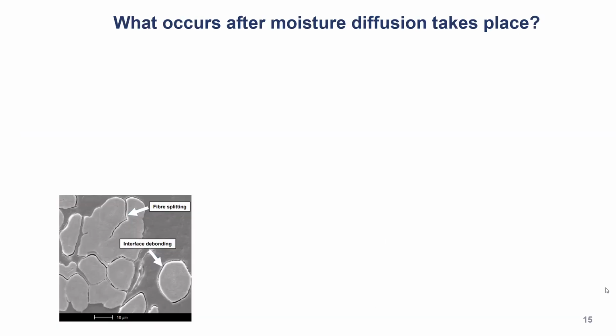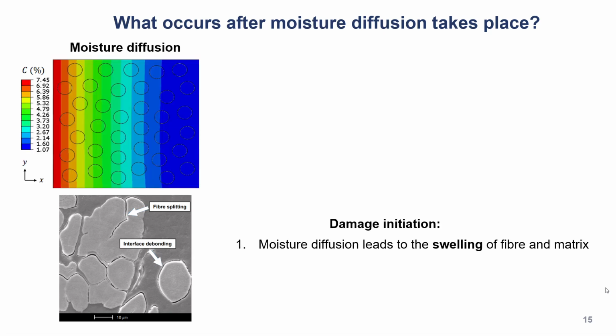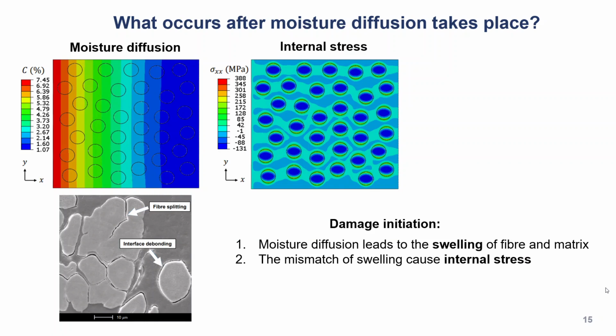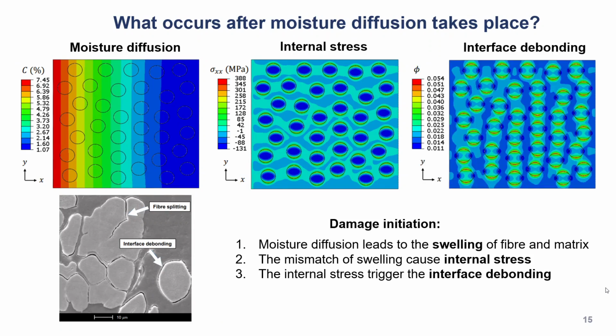The first question we want to ask is, what occurs just after moisture diffusion takes place? If you look at the experimental results, you can see some fiber matrix debonding occurs. And this can be explained by this failure sequence. You have the moisture diffusion. This can cause internal stress due to the mismatch between the fiber and matrix coefficients of expansion. They can have different internal stress, and this can promote the interface debonding. That's the first thing that happens. Before you do mechanical characterization, it already triggers some internal interface debonding here.